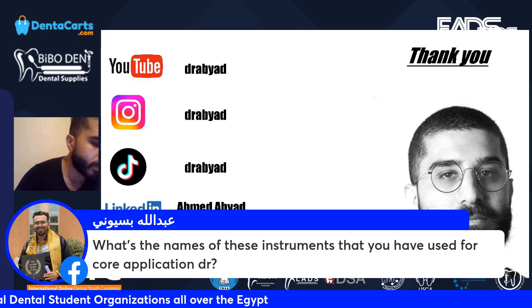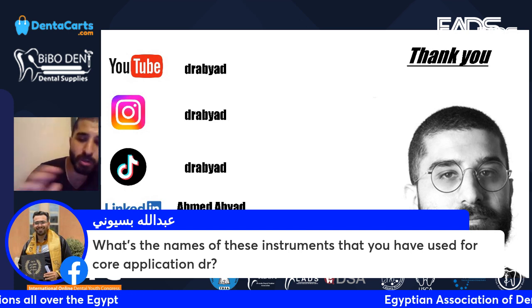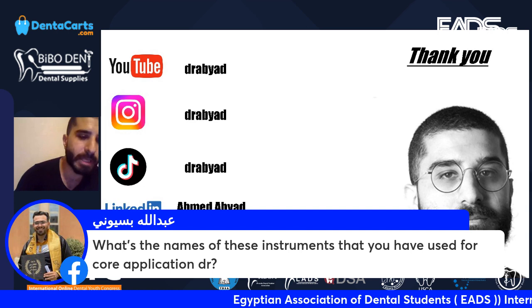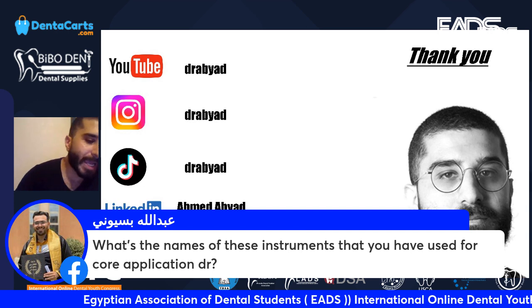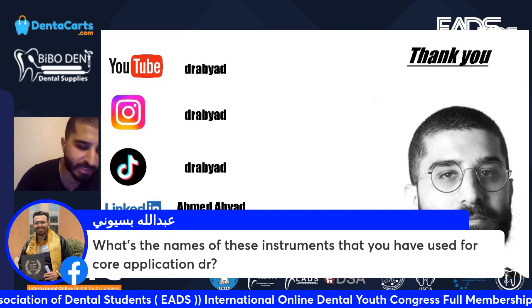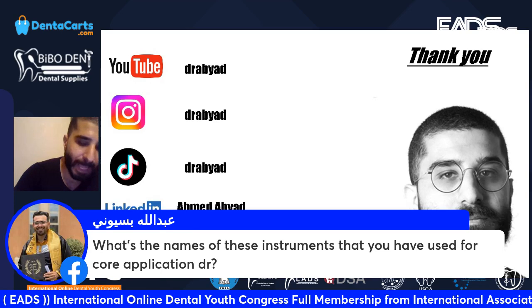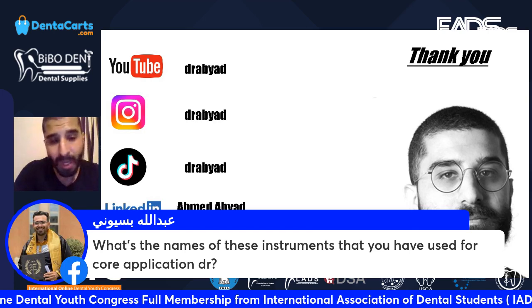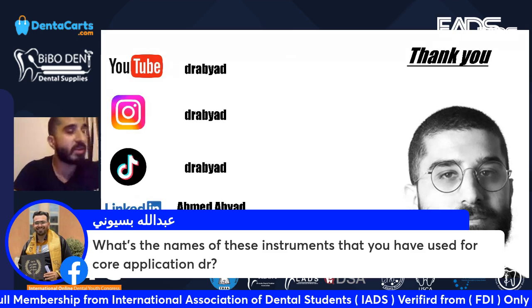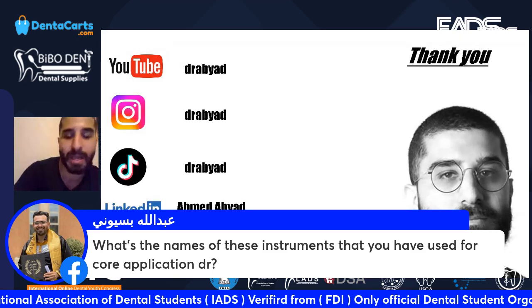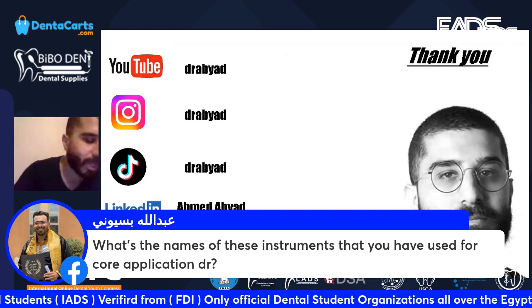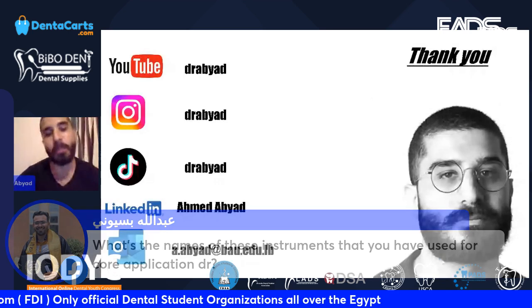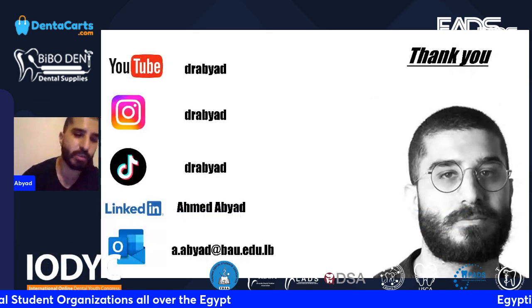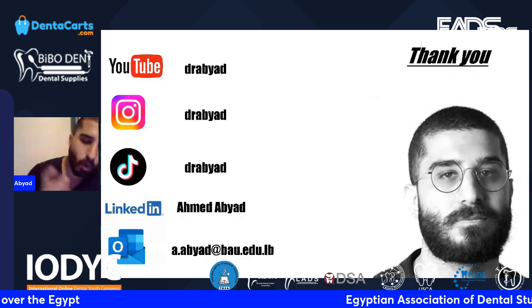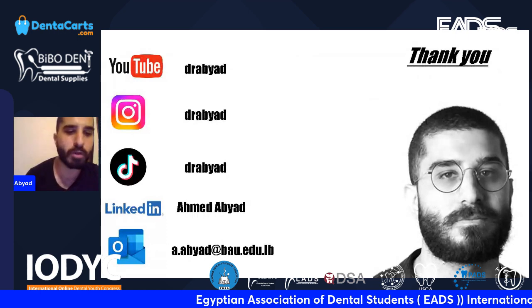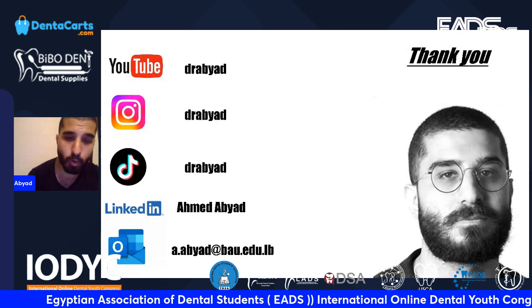But in the end, I want to tell you that it's true that in the literature, the failure rate of the fiber post is extremely high. But I can tell you from personal experience, if the fiber post is placed well, I don't think that you will experience failures. On the contrary, I always believe that whenever you can place a direct filling, or whenever you can do a direct procedure, do it. It's much better than going for an indirect procedure. And we have lots of evidence on that in the literature. Always, when direct is possible, go for direct, if you can follow the correct protocol.